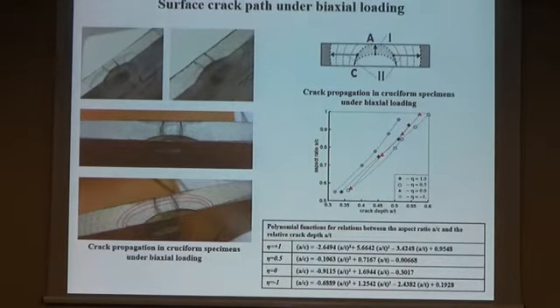In this figure, you can see the experimental crack front positions as a function of accumulated numbers of cycles of loading. And these results show that the fracture process in cruciform specimens can be divided into two stages. On the first stage, crack propagates like a surface, semi-elliptical crack, and on the next stage, the surface crack completely crosses the specimen thickness, and then crack propagates as a full thickness crack. So on the basis of these experimental results, we obtained the relationships between aspect ratio and the crack depth.